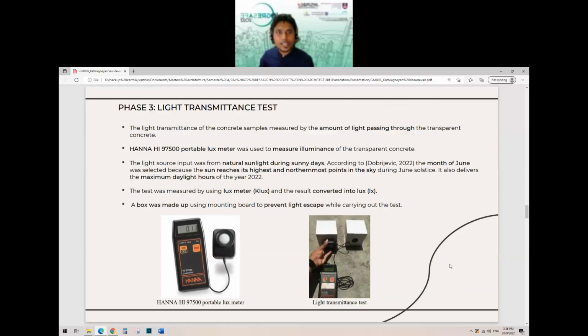So for phase 3, the light transmittance test. The light transmittance test was measured to see the amount of light passing through the transparent concrete. The equipment used was a portable lux meter to measure the illuminance of the transparent concrete. The test was measured in kilolux, and the result was converted into lux. A box made of mounting board was used to prevent light from escaping while carrying out the test. The picture below shows the equipment and how the test was measured.